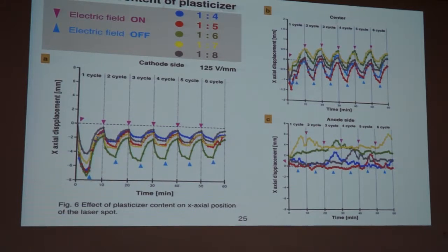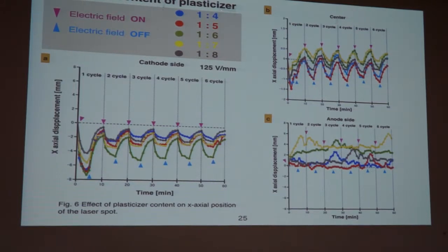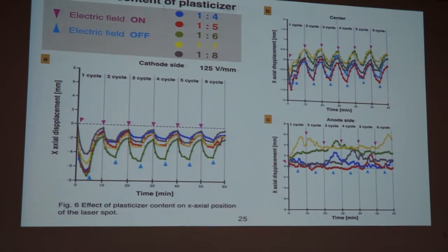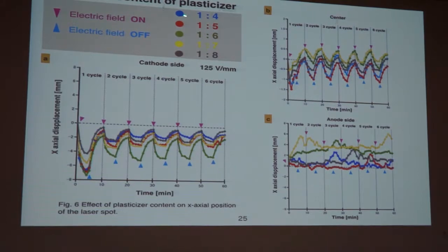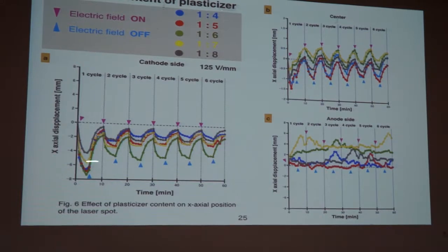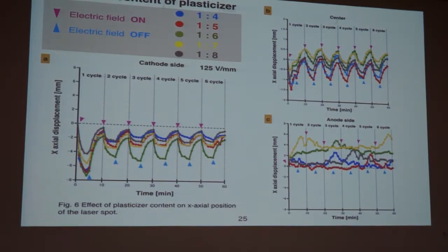The influence of the content of plasticizer is shown here. When we change the content from 1 to 4 in weight ratio, PVC to plasticizer, then I change it this way. And at a certain position, in this case, for example, green, 1 to 6, the maximum diffraction is observed. So it depends on the plasticizer. The small one and the larger one, too large, is not effective for diffraction.